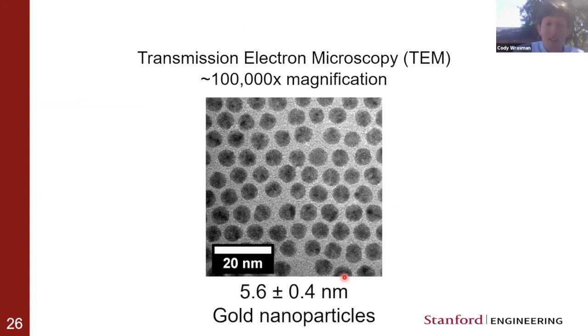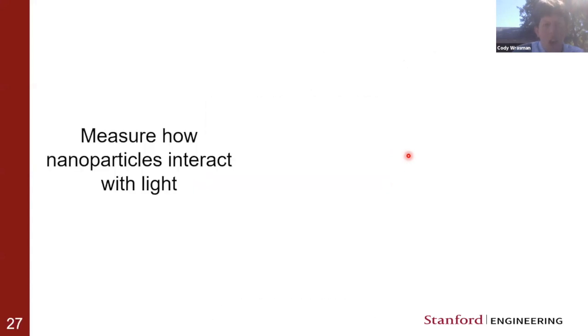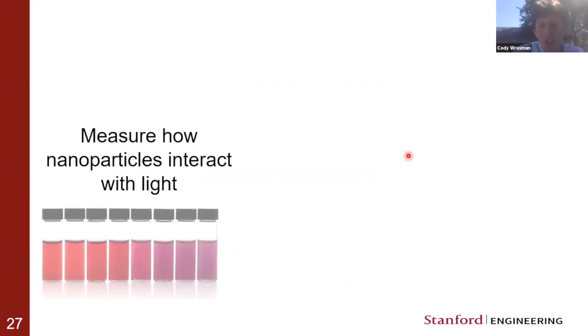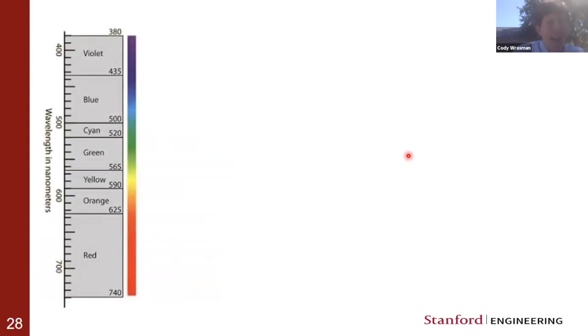This enables us to have images with magnification over hundreds of thousands of times better than the human eye. It works very similar to typical light microscopes, only instead of light, electrons are used. Here I'm showing you some TEM images of gold nanoparticles that we would use as carriers for those single palladium atoms. Another thing that we can do with gold is measure how those nanoparticles interact with light. I think Angela showed you yesterday the instances of gold nanoparticles and how their color can change with different size. We can use that to characterize these nanoparticles.